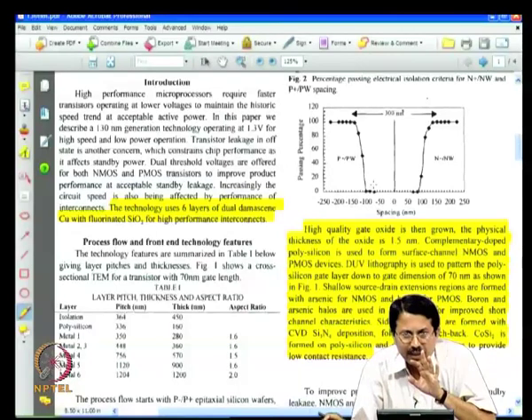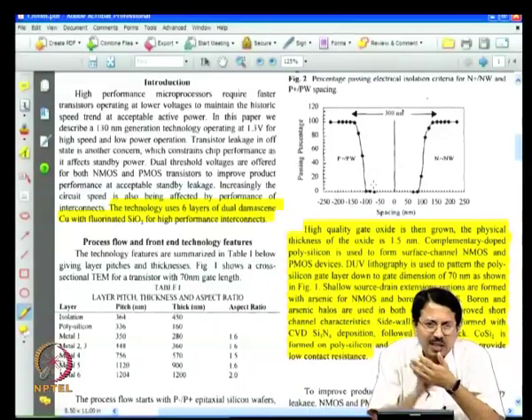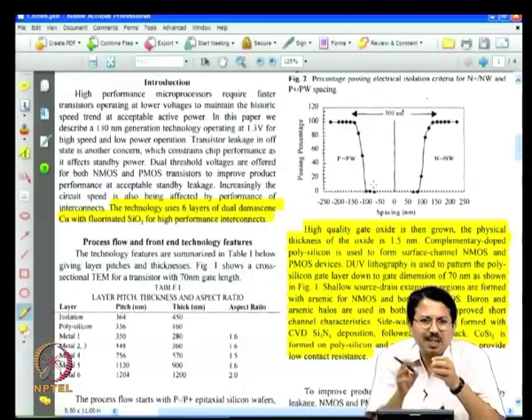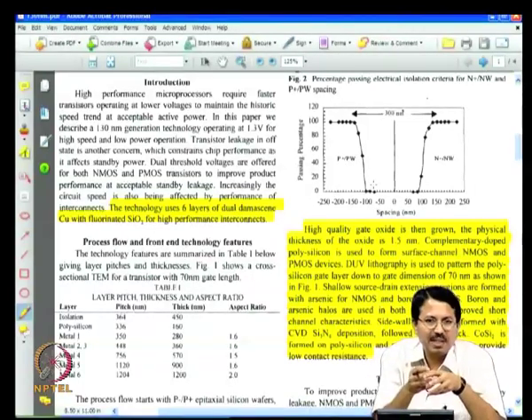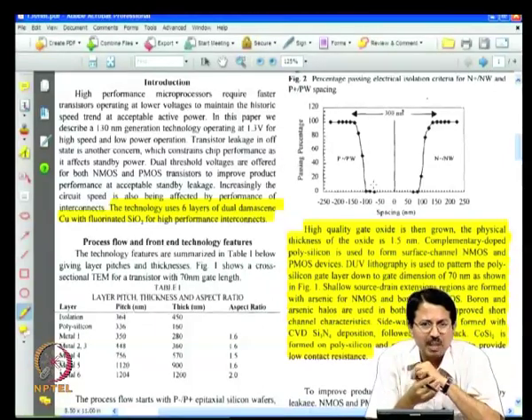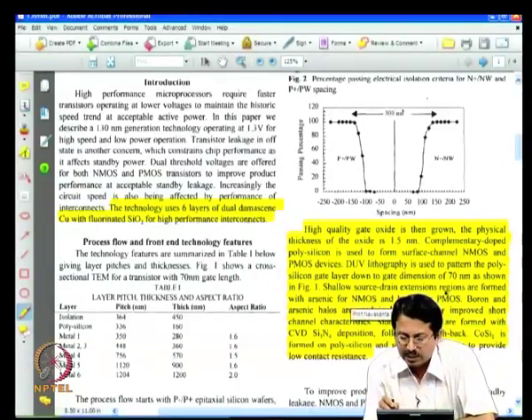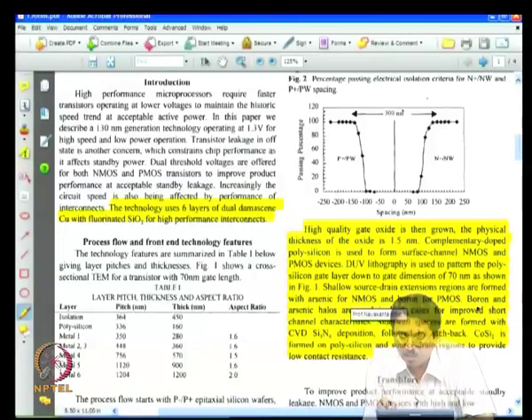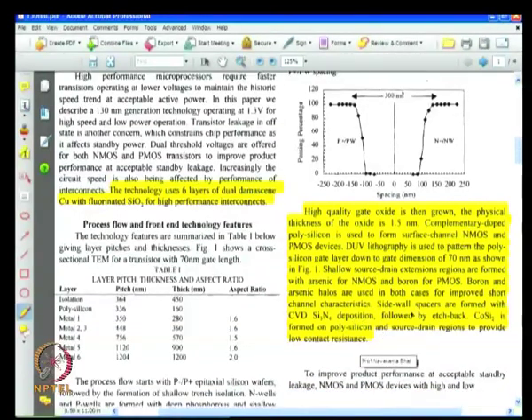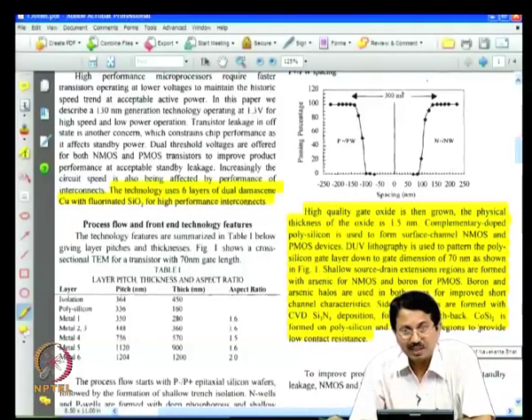All else will remain identical. You will use halo, you will use shallow extension, except that you may change the dose, because the transistor gate length is going down, especially the halo dose you may want to manipulate. Shallow source drain extension regions are formed with arsenic for NMOS, boron for PMOS, boron and arsenic halos are used, this will remain the same. Silicon nitride is used for the spacer, followed by etch-back. The silicide here is cobalt silicide as opposed to titanium silicide. Cobalt silicide gives you much lower resistance compared to titanium silicide.